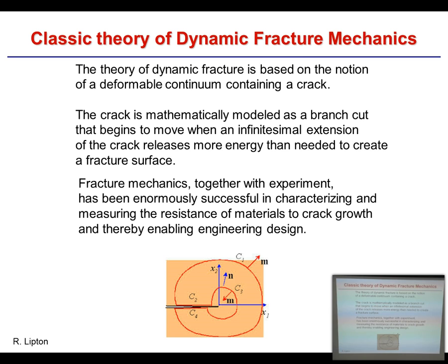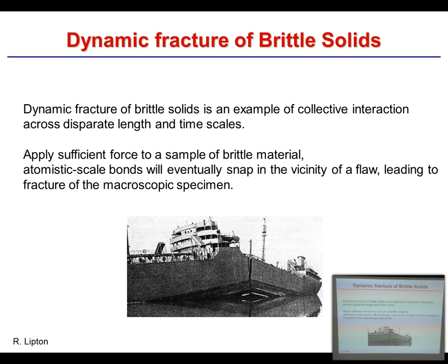The classic dynamic fracture theory has been tremendously successful. Basically the crack is modeled as a branch cut with an elastic solution on either side of the domain. The crack begins to run when it releases more energy than is needed to create new surface — once you release more energy than it costs to generate two surfaces, the crack will run. This was extremely successful and has enabled engineering design of many things.